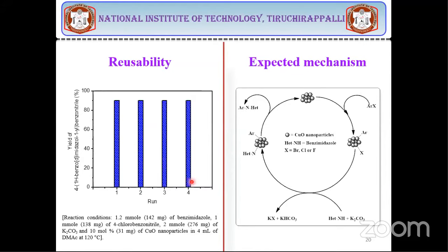here only 4 times. You see here, the catalyst can be recovered very easily and can be reused for many cycles without loss in the activity. You see here, the yield in all these cases is around 90%. There's no loss in the activity, even if you reuse the catalyst, right? So the copper oxide is active like homogeneous here, and also like heterogeneous, the catalyst can be easily separated and